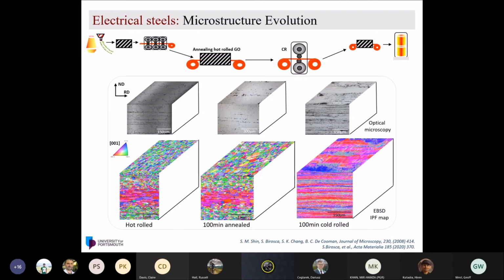Okay, next. So now microstructure evolution, this is the work we did with Sunmi and the late Professor De Cooman. As we see, the microstructure evolution through the hot rolling and cold rolling is a bit complex, and mainly the surface microstructure is very different from the microstructure in the cross section, because of the huge strain and temperature gradient across the cross section, which, especially in hot rolling conditions, gives dynamic recrystallization, and some of the grains at the edge or close to the roller will recrystallize faster than the ones in the middle.